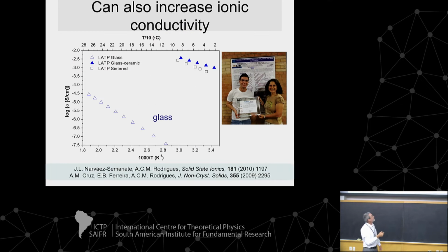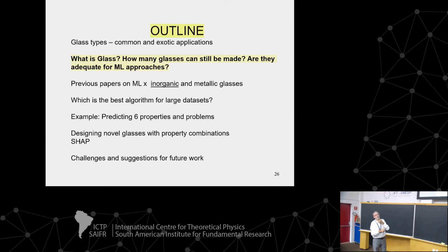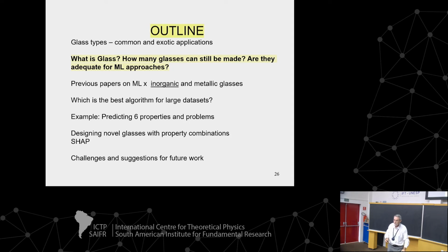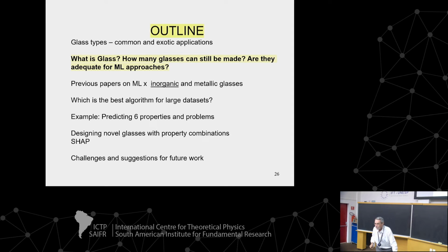That's what happens, for instance, here. This is a glass with crystals inside percolating. So we have a nice path for electrons, or for ions. In this case, it's ions, lithium ions. Does it become less ductile as a result? Less ductile? No, it becomes more ductile. The K1C, which is the critical stress intensity factor, increases also. So we improve the ductility also by partially crystallizing.